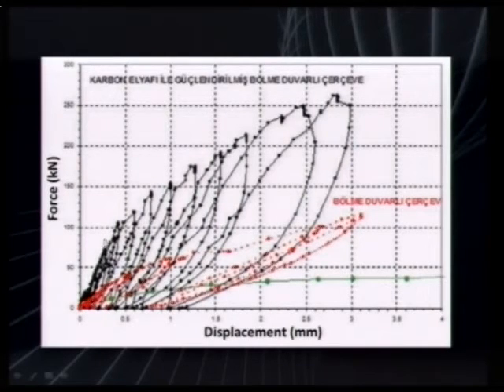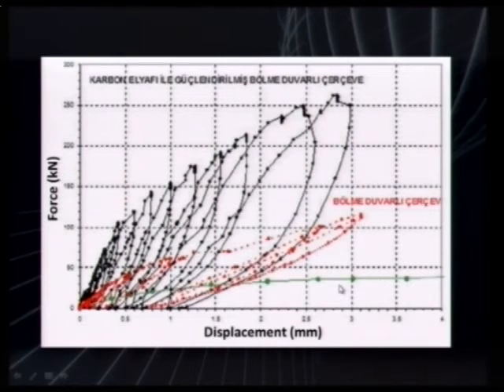And when we look at the backbone of the cyclic experiments here, the black one is the one with the CFRP application. The red one is where there is no CFRP application, and the green one is actually the bare frame. There is no infill, in fact, inside the RC frame. So we can see here that the strength and stiffness of the structure increases tremendously when you apply the CFRP and when you are successful enough to integrate the infill walls to the RC structure.